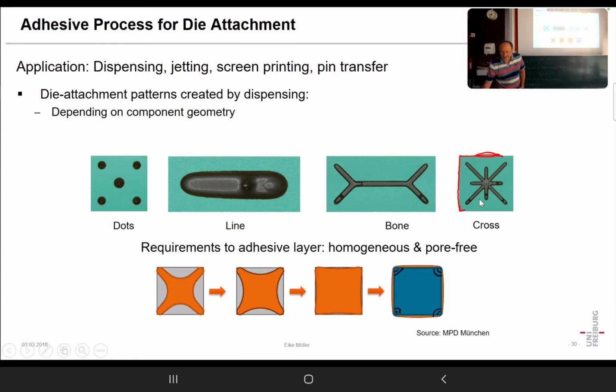For instance, we print that way, then we put on the chip, and the material is pressed to that outside, coming out, and finally, the best is when maybe it just goes out just a few micrometers over the size of the chip. Then it's optimum printing, and that means the proper amount must be brought there, and we must have the proper pressure in the placement of the chip.